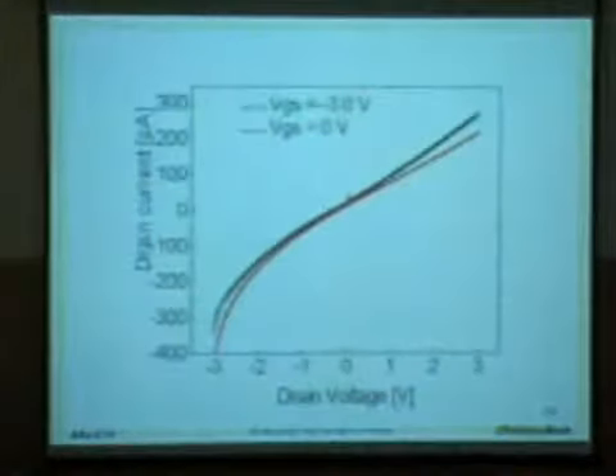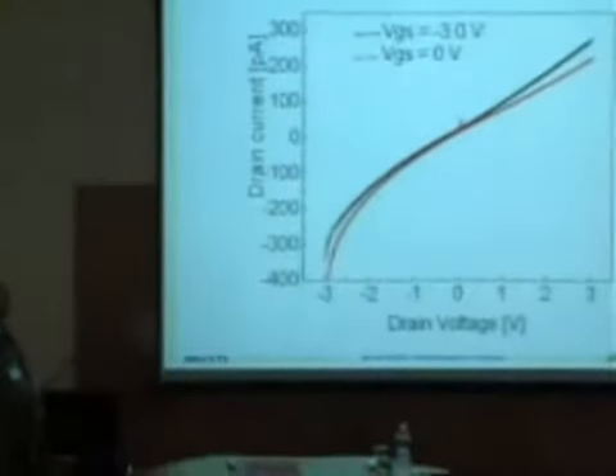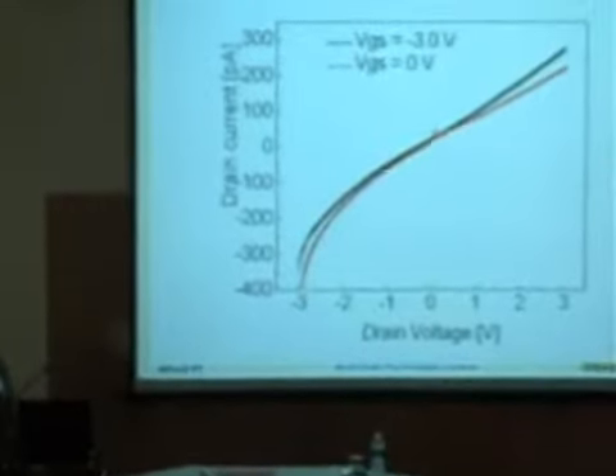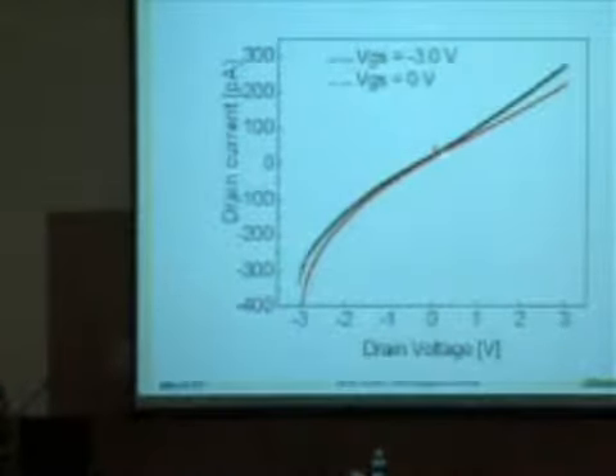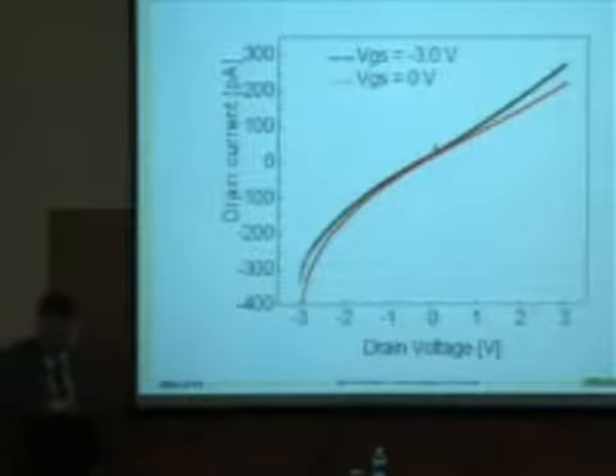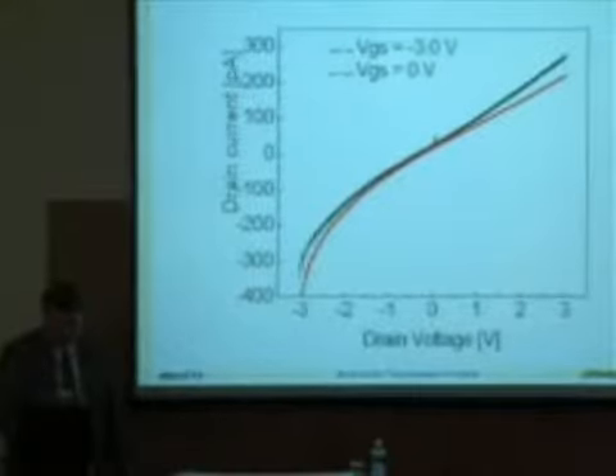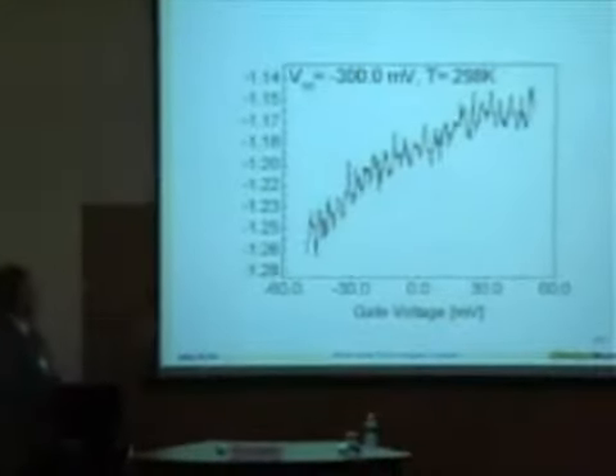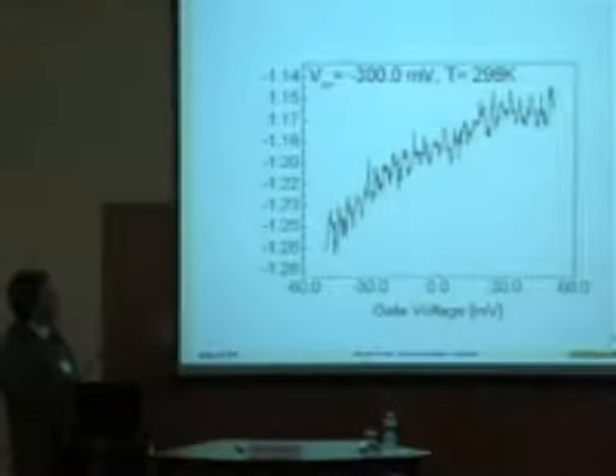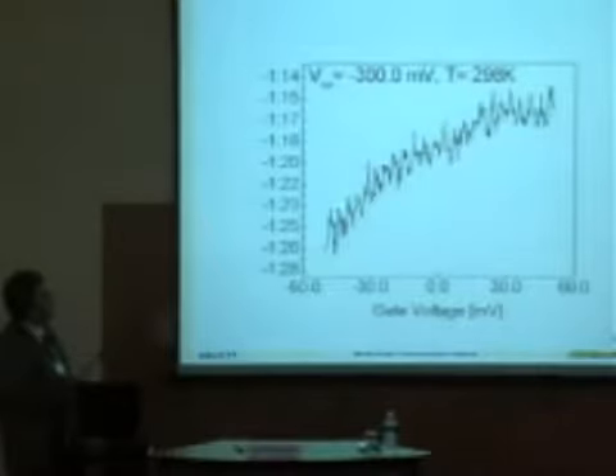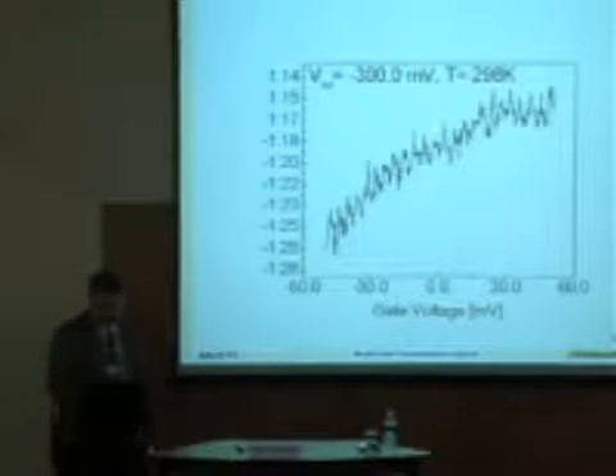And we see that, as we saw with the reference source, about zero gate potential and zero drain potential, we see curvature in our conductance, and that's indicative of this quantum behavior in the SET. And that is confirmed even further as we look at a small scan across gate voltage, and we see this behavior of Coulomb blockade taking place in our drain current for a given source drain voltage. This was measured at room temperature, and we do have measurements that have also been taken at lower temperature to look at comparing and trying to understand the behavior of the devices.